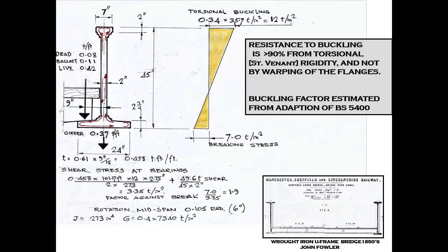And I've got up the factor of 0.34 as a buckling resistance. I adapted BS5400 to try and take, I say try because I don't know there's an established theory for this, but using equivalent lateral flanges in warping to represent the torsional rigidity, a bit of a fiddle if you like, but I end up with this factor of 0.34 times the ultimate stress in compression of cast iron and getting about 12 ton a square inch. I've worked out as well the internal shear stresses, which would peak, of course, at the end of the girder as the torsion built up towards the end, and I get a factor of about 1.9. The internal shear stresses due to the torsion plus vertical shear, adding up to about 3.35 tonne a square inch. So it looks as though the girder wouldn't fail in torsion.